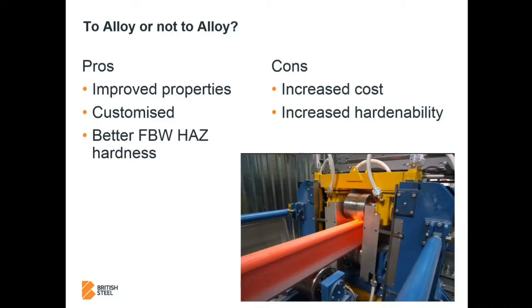So for a given cooling rate, you can get a harder pearlite with chromium alloys, because on your continuous cooling diagram, it shifts your pearlite nose to the right. So you end up with a finer pearlite for a given cooling rate. So it does improve the hardness of your weld's critical HAZ, which is desirable in some heat treated grades, and we'll explain that later. The cons though: increased cost. It's not a vastly expensive alloy, chrome, but when you're buying thousands of tons of this stuff, incremental costs like that do mount up, and it does increase the hardenability, so you lower that tolerance to a wide range of cooling rates. So it means that the welding becomes more critical, that it's controlled precisely.